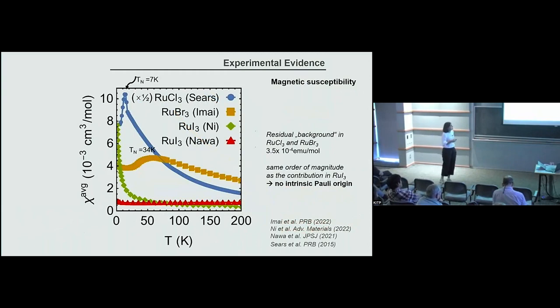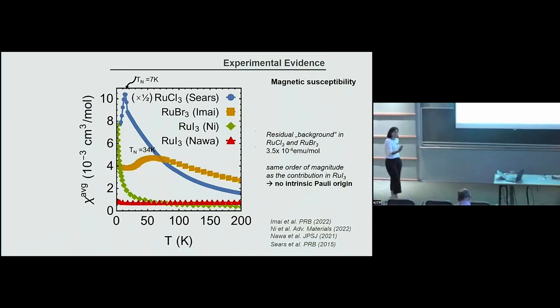For the susceptibility of the three materials, ruthenium trichloride and ruthenium bromide do what we expect when the system orders at low temperatures. It shows a phase transition at 7 Kelvin for the chlorine, and for the bromine, the phase transition to an ordered phase, which is also a zigzag ordered phase, is at 34 Kelvin. However, if you look at the two samples of ruthenium iodide, it looks like Pauli-like behavior, so it's very flat. In one of the samples, there is a rise in the susceptibility, which has to do with the fact that there are some magnetic impurities. So the question is, is this because it's a metal?